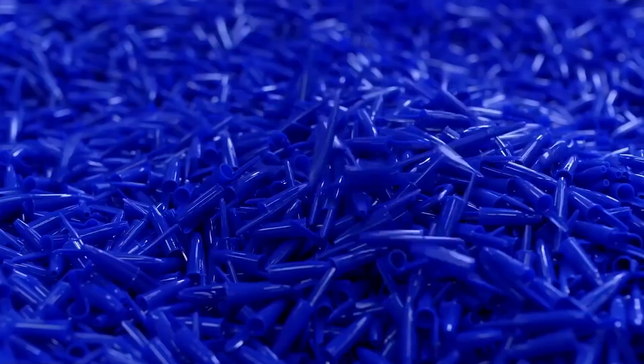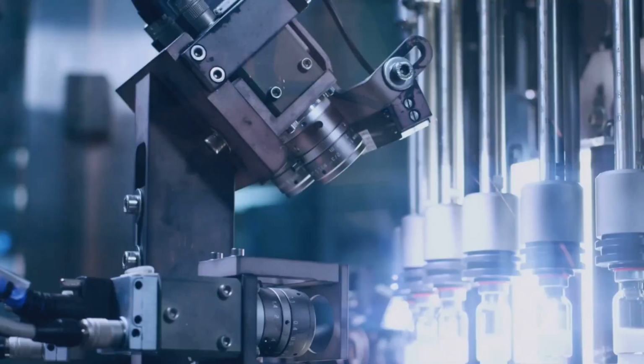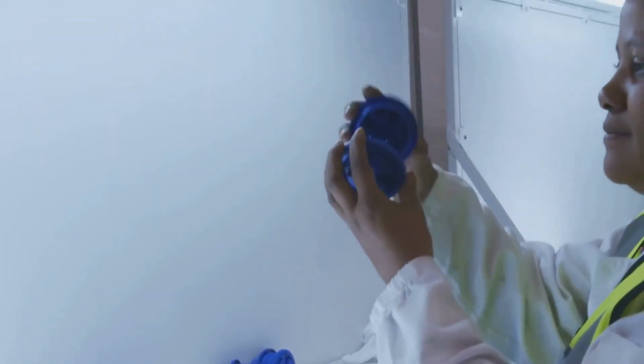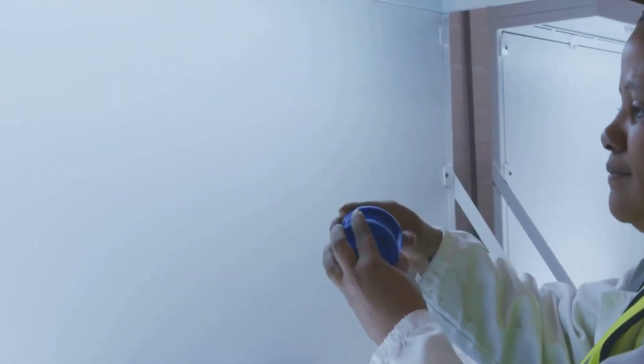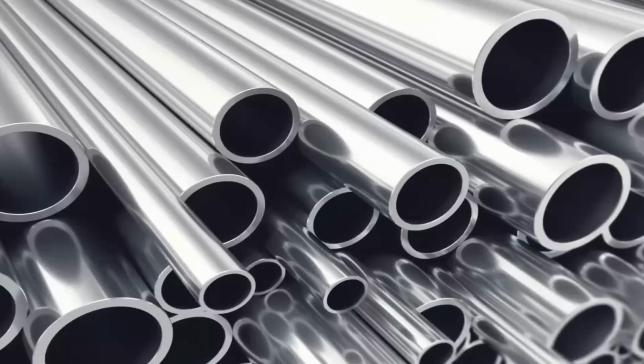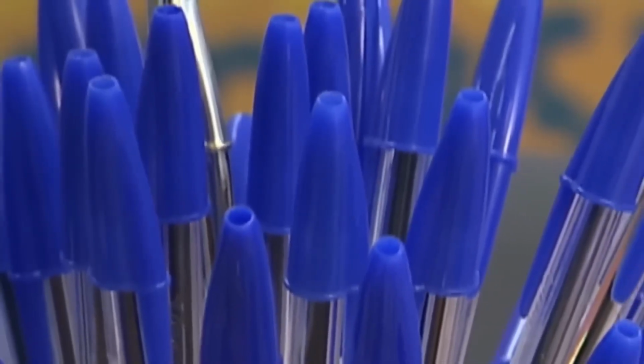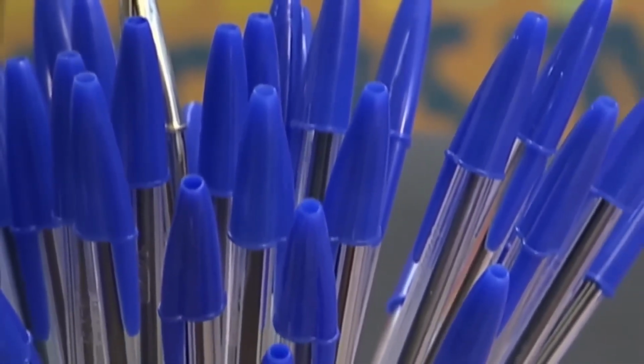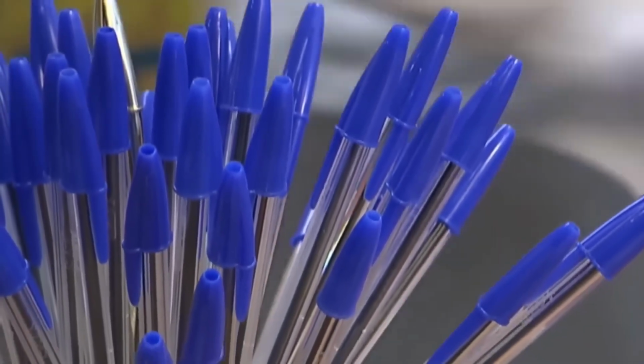From a 3mm polypropylene pellet to a pen writing 2 to 3 kilometers of continuous line. The Bic Cristal passes through injection molding at 1200 bar, ball grinding to 1 micron roundness, ink formulation at 15,000 centipoise, and laser inspection at 40 pens per second, all to reach a retail price of under 20 cents.